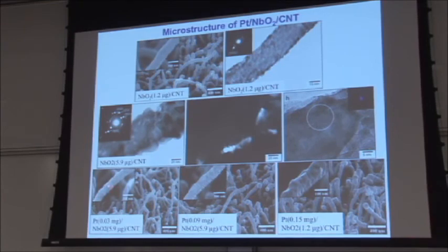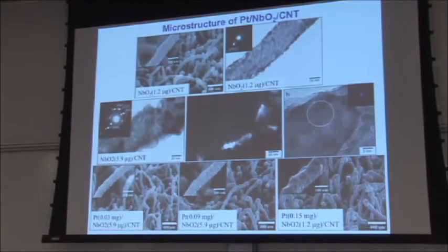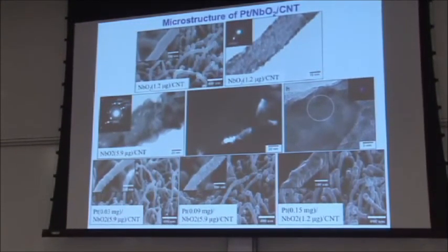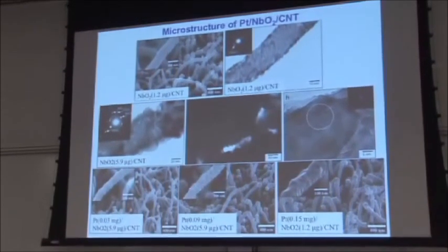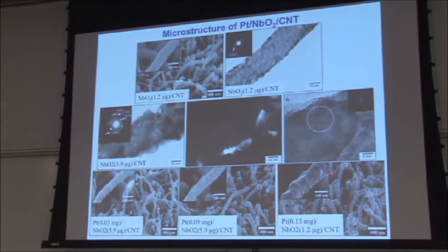And then when you deposit the platinum on the niobium oxide, which actually is a classic textbook example of strong metal support interactions, platinum on a reduced niobium oxide, you have excellent wetting of the platinum metal on the niobium oxide. So the morphology looks fundamentally different with the exact same mass loading of the platinum that it did on the carbon nanotubes by themselves.